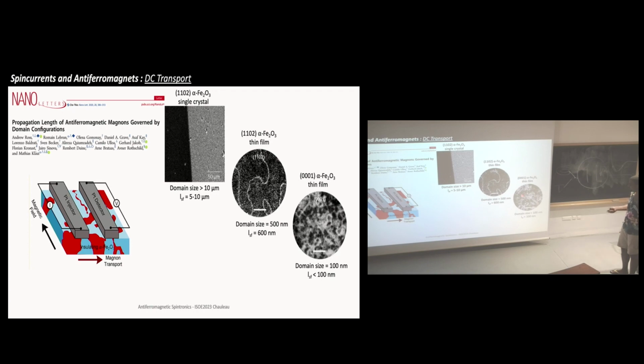So for example, if you take this one, this is the single crystal, it is written here, and then this is the thin film with, let's say, large domain and very thin domain, and you see that the spin diffusion length is really decreasing. So that means that to some extent, having very large antiferromagnetic domains is very important if you want to carry the information over a long distance.